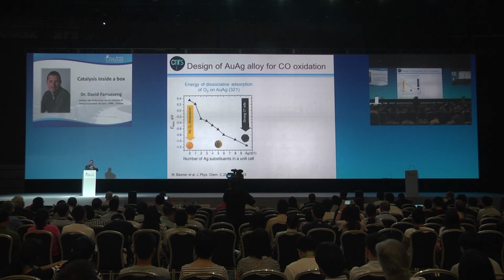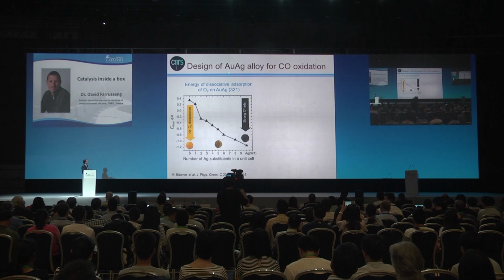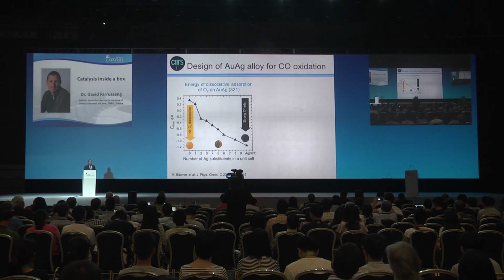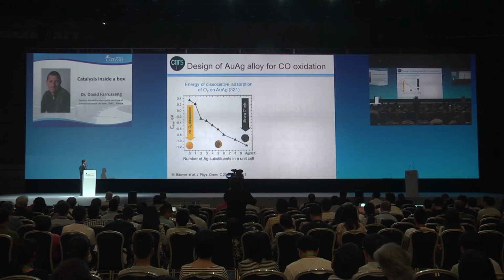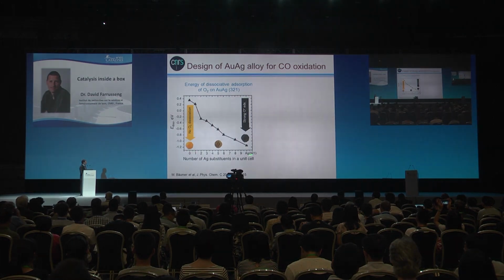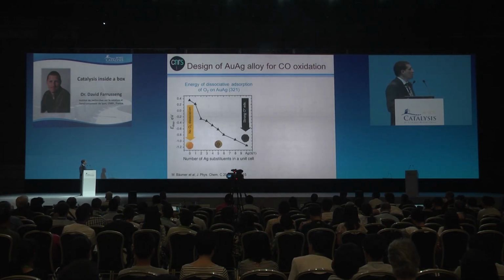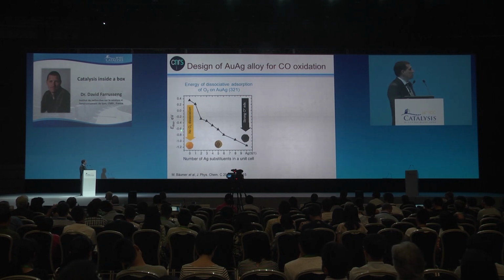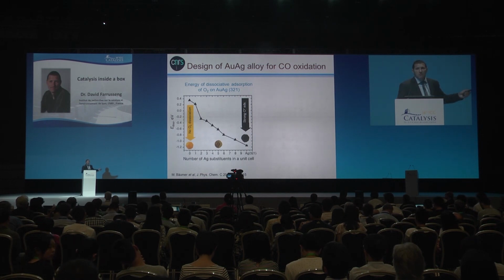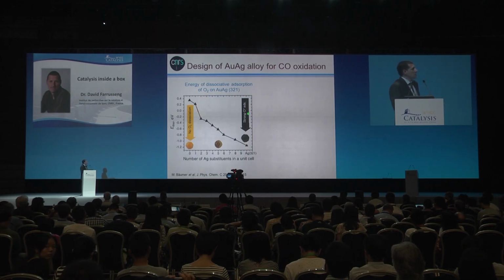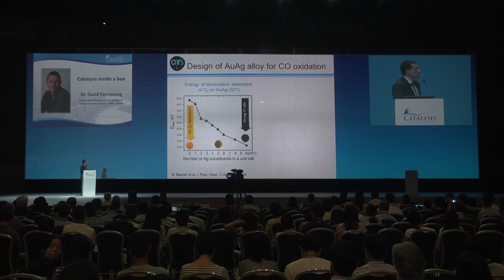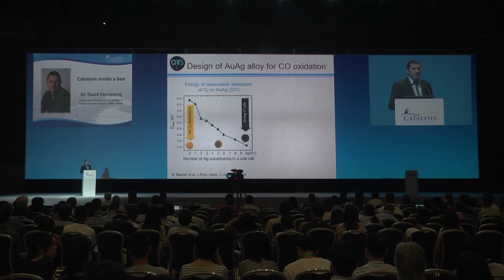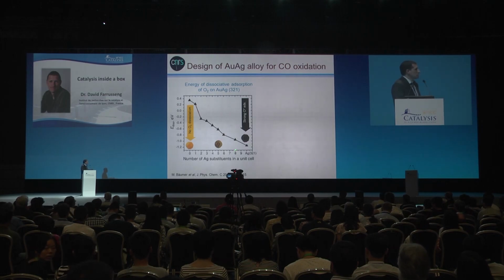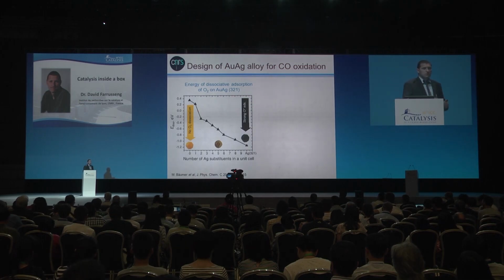But still we wanted to know whether we had at the surface both, for example, in this case, silver and gold, and for that we have selected CO oxidation, which is going to give us a fingerprint of that. So we know from the basics that here it's gold nanoparticles, here it's pure silver, and here it's a mixture, an alloy. We know that oxygen does not dissociate on gold, and it's a poorly oxidizing catalyst, obviously. While silver dissociates oxygen very strongly, and there is no room here for CO to react. So it's also a poor catalyst for CO oxidation at lower temperature. So it is known that it is for mixtures of 50-50 or a 2-to-1 ratio between silver and gold that you get the maximum activity.